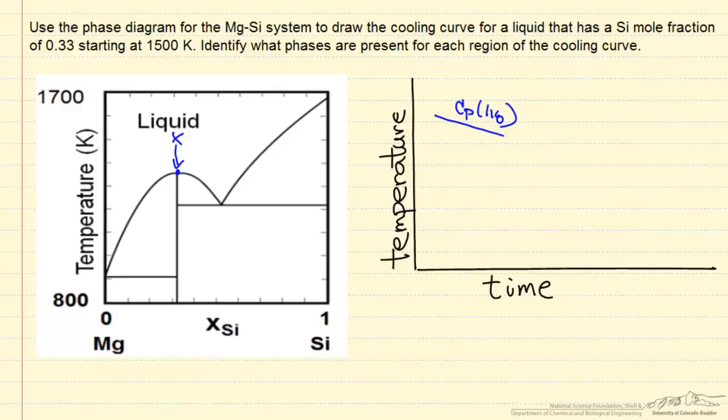We get to this point, now everything in terms of phase change takes place at one temperature because below this, what we have is this compound, Mg2Si. Now we're going to have a horizontal line corresponding to the delta H for this compound, the heat of fusion. Once we've made all the compound at this temperature, which is about 1360 Kelvin,